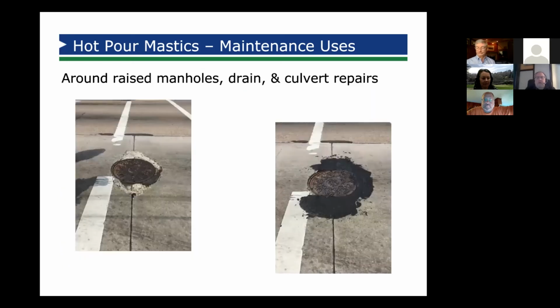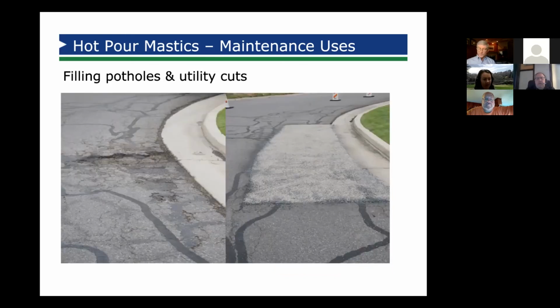Good point. Rick, one question on the topping that we're seeing in the photograph to the right. Because of the way the binder is manufactured, the topping adheres to it. It doesn't try to repel away from it like some other similar material. Unlike a crack sealant material that has resilience or pushback, there is less of that in a mastic mix. And so we find that you can embed an aggregate on top of it. The truth is, however, traffic's going to wear that off probably within the first 30 days, and that'll all turn black again anyway. But for some manufacturers that may have a segregation problem, a topping stone will assure that you have a nice friction course on top as well. But I like to think of it more as a protective coat, or just putting the top on that so that it will last longer.